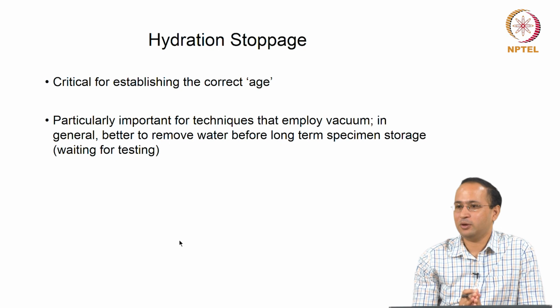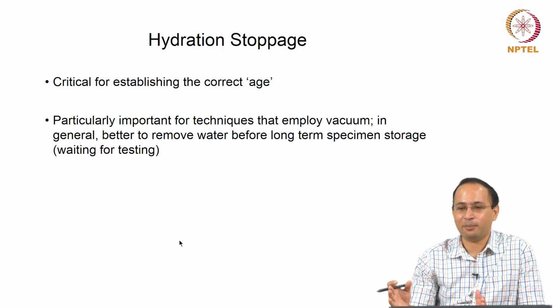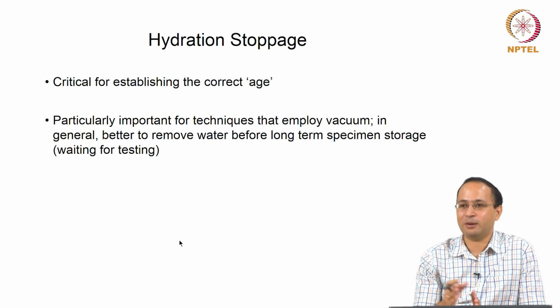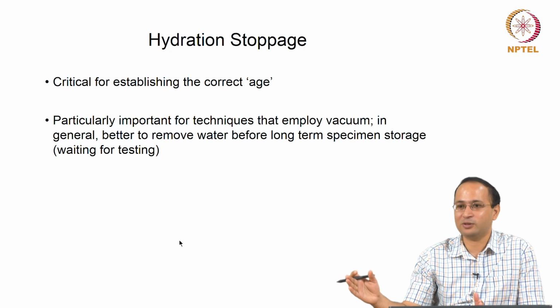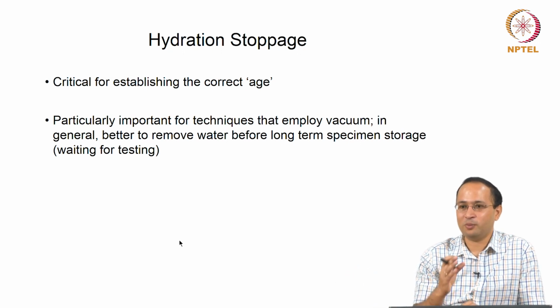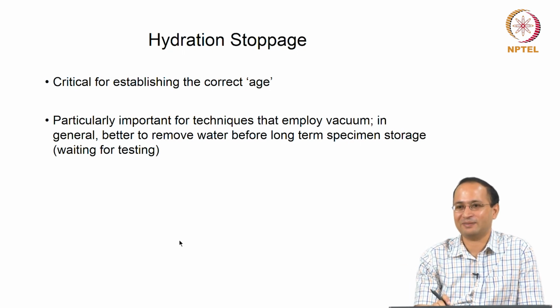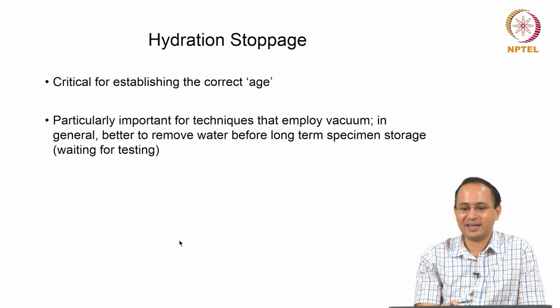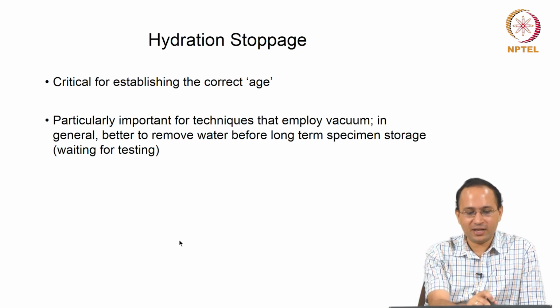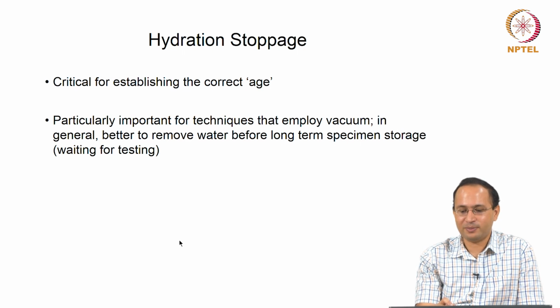If you want to understand the effect of degree of hydration, if you want to compare different samples, you are talking about a 1 day old sample, 7 day old sample, 28 day old sample, right. So you have to make sure that you collect the sample and stop the hydration so that no further hydration takes place. Also particularly important for techniques that employ vacuum. Other techniques may need vacuum, so you have to make sure that your sample does not have moisture. So in general, it is better to remove water before long term specimen storage.